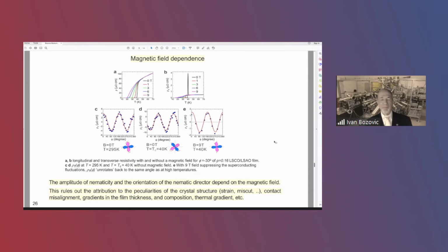Another very incisive probe that we have added recently is transverse magnetoresistance. In zero field, the transverse resistivity has a peak near Tc. When we apply a magnetic field, the resistive transition fans out like this, and the peak in transverse resistivity is suppressed by an order of magnitude. The transverse conductivity increases by 1000%. And for this reason, in analogy to the well-known colossal magnetoresistance, you may call this colossal transverse magnetoresistance. Interestingly, in this sample, at this field, we see essentially no magnetoresistance in the longitudinal channel.